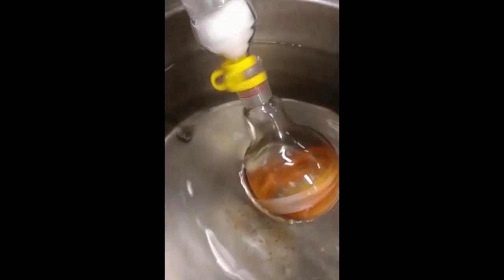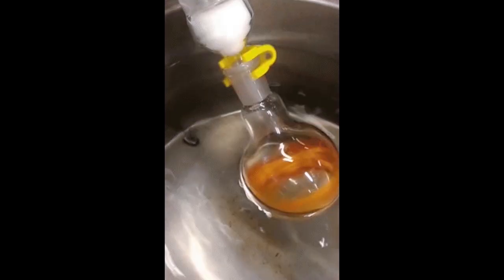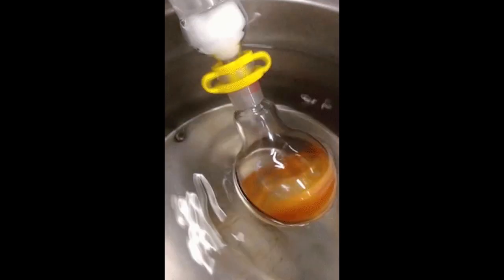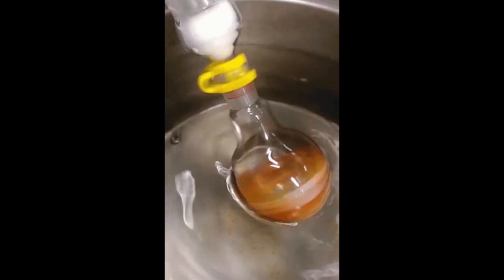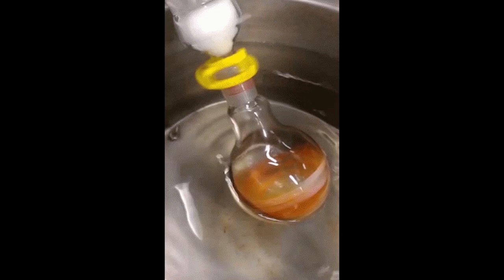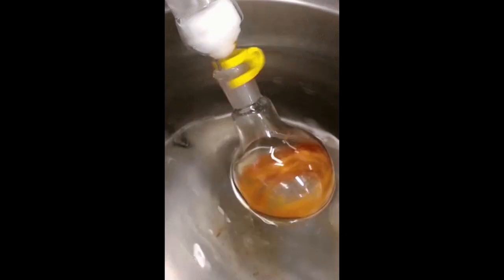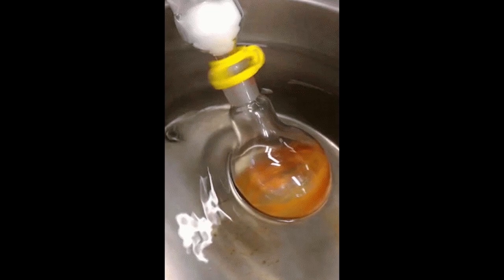For instance, lipid molecules dissolved in an organic solvent can be deposited as a thin film onto the wall of the container. Upon hydration with an aqueous solution and gentle agitation, liposomes spontaneously form as the lipid film rehydrates and closes into vessels.